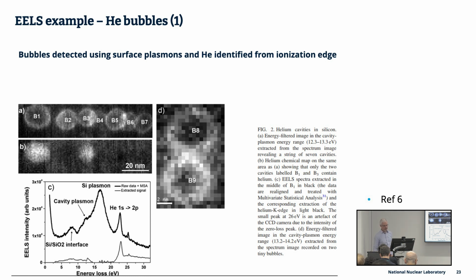This is an example, it's not a nuclear example, unfortunately. It's from helium-implanted silicon, but it shows silicon, the plasmon's at 15 eV, but the helium ionization edge is quite distinct from it. And that allows you to produce a map like this, which shows that only these two bubbles out of this chain of 7 have actually got any helium left in them. The others must have intersected the surface of the sample and just become punctured during the course of the sample preparation. The other thing that it shows is there's a surface plasmon which is specific to the bubble to matrix interface. So it shows you that they're proper cavities.